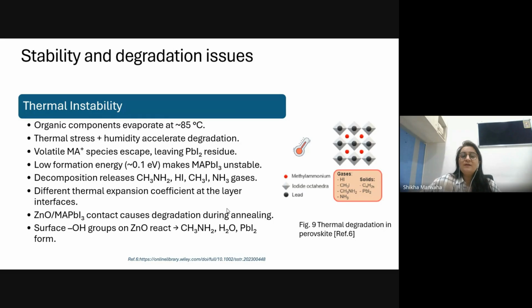Another thing that has been seen is at the ZnO, that is zinc oxide, and methyl ammonium lead iodide interface. Any absorber layer has to be integrated with the electron transport layer and hole transport layer. We have seen that when we use zinc oxide as one of the transport layers, at the interface there is a degradation happening due to annealing. When we are increasing the temperature, there is a degradation.